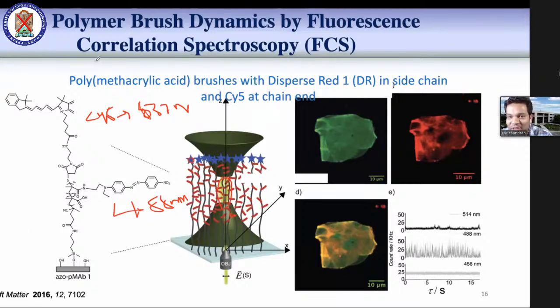We use fluorescence correlation spectroscopy. This is one of the powerful tools in correlation and confocal spectroscopy, where you can gather a lot of information. So here, when we use 488 nanometer, the signals are coming from the azobenzene molecules, and 633 signals are coming from the cyanine 5 molecules. When we excite from the lower wavelength, 458 nanometer, you can see that there is no fluctuation or dynamics observed.